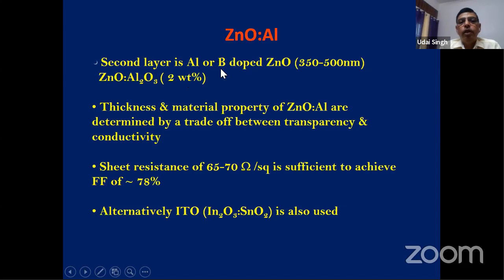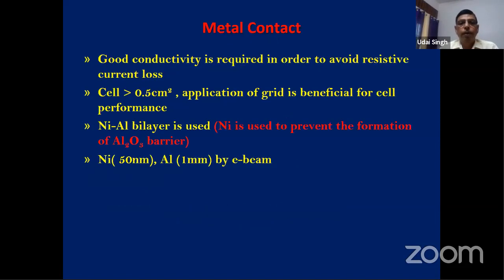The second layer is aluminum or boron doped, 350 to 500 nanometer thickness. The thickness and material property of these determine the trade-off between transparency and conductivity, as I told you earlier. Because if you want more conductivity, your transparency will reduce. So there is a certain trade-off. You have to optimize between 80 to 90% transparency and conductivity of a certain range. And finally, if you are trying to have a large area, you put certain metal contacts so that you can collect the current from all over the area.